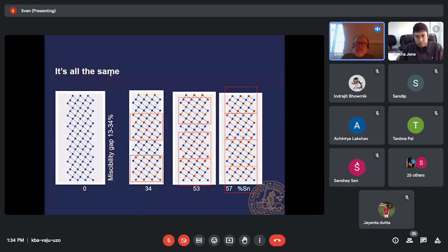These have a composition which isn't that of rock salt 1-to-1 because of the limited size of the blocks, which is just 7 layers. So this is Sn4Sb3, and then there's an admixture of antimony in between.